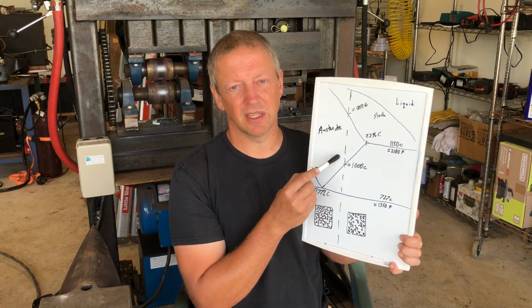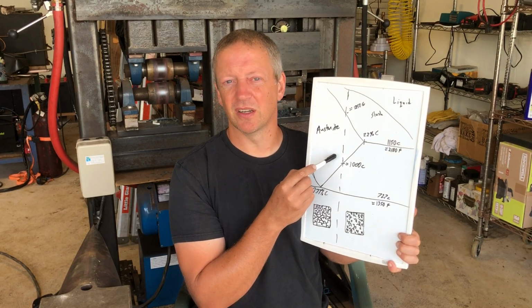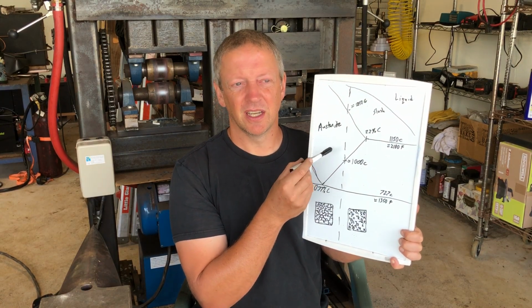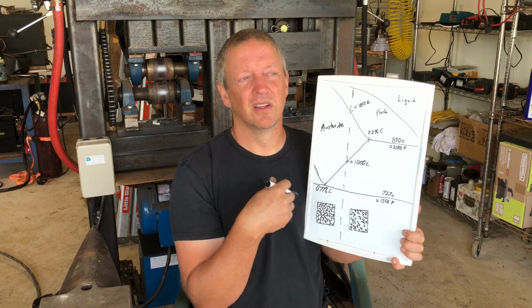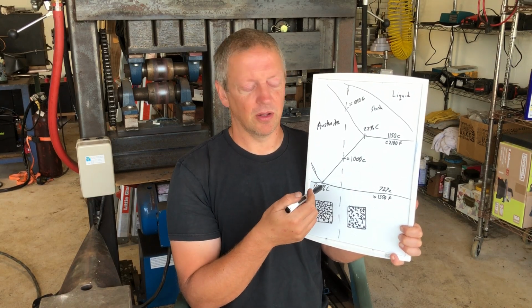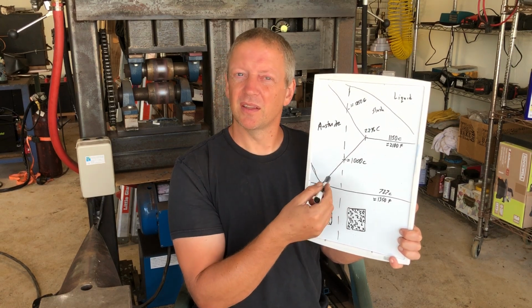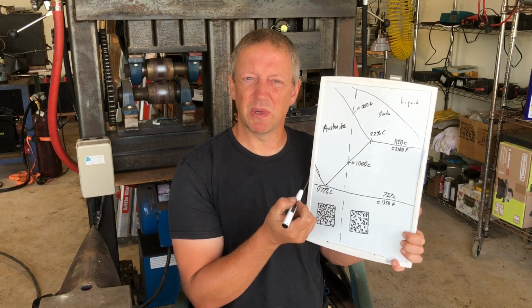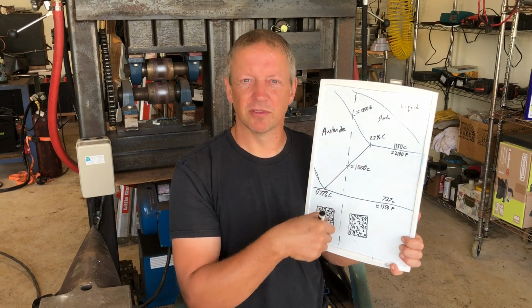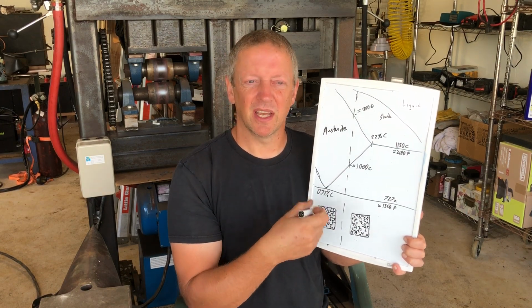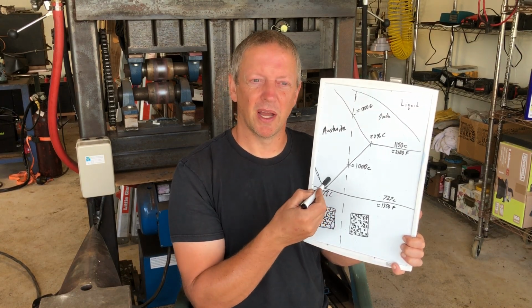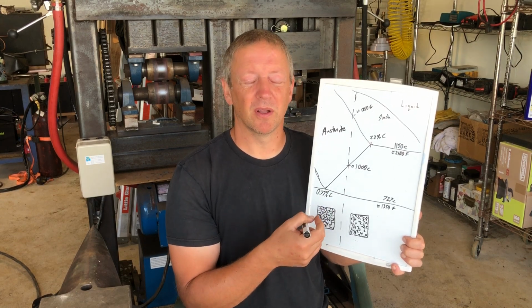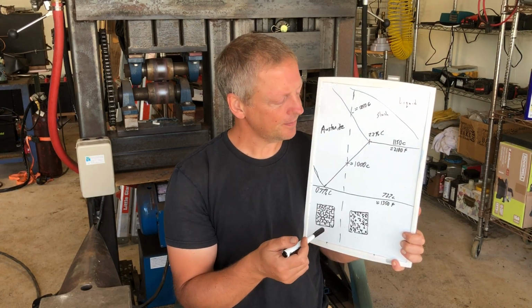You can still get large carbides in this scenario, because the larger a carbide is, the longer it takes to dissolve. So once you start to get large carbides, they tend to be self-reinforcing. This is referred to as Ostwald ripening: the idea that over many cycles, the larger carbides grow at the expense of the smaller carbides.